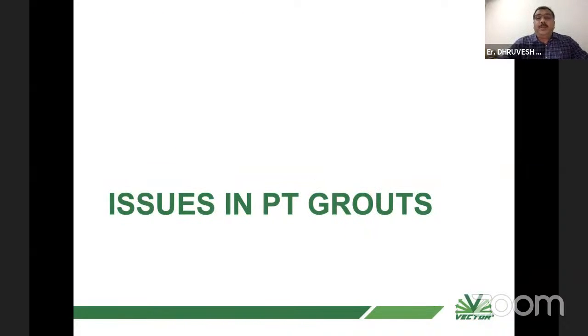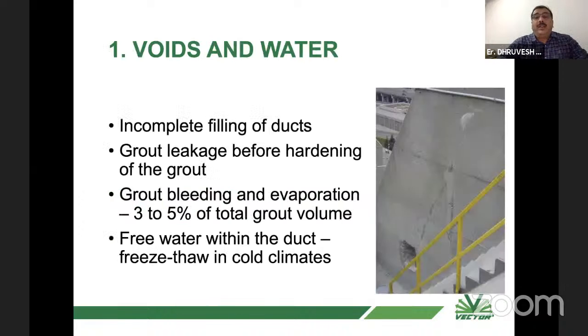Mainly, what are the issues in PT grout? Whenever you have post-tensioned grouted tendons, there can be voids and water. You can see water coming out from one of the PT tendons on the right hand side picture. This is because there can be incomplete filling of the duct, grout leakage before hardening of the grout, and grout bleeding and evaporation, which may be up to 3 to 5% of total grout volume. This is found if it is cement water grout. But I have come across cases in India where the percentage of voids is even far more than this.